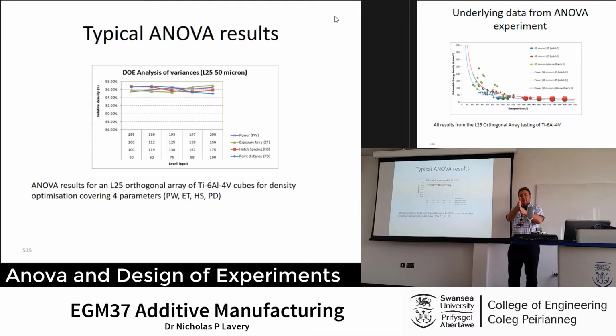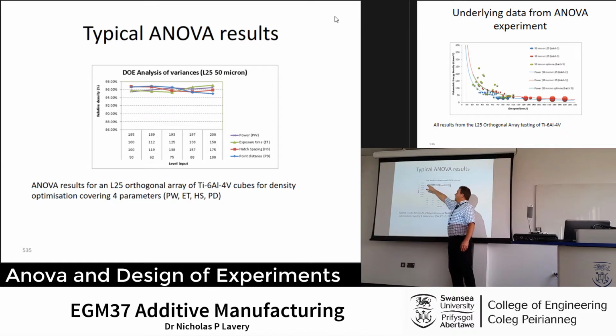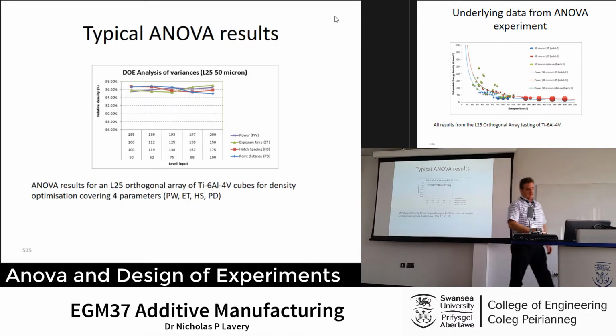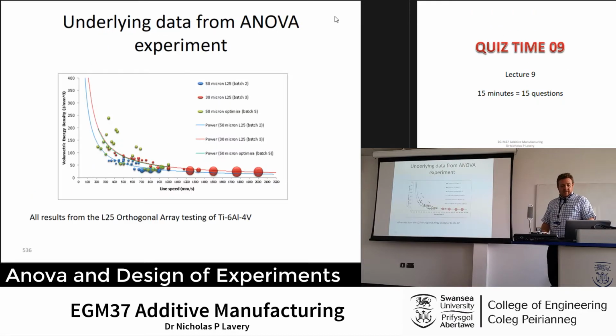And that having an overlap itself could be detrimental sometimes to the density. It actually causes each of the beads then to kind of slump. So what we were finding here is that you actually had a big variance on either side of the extremes of the hatch spacing. And that was coming up with the ANOVA results. Well, at first we couldn't think about why it was, but it wasn't until later that it became clearer.